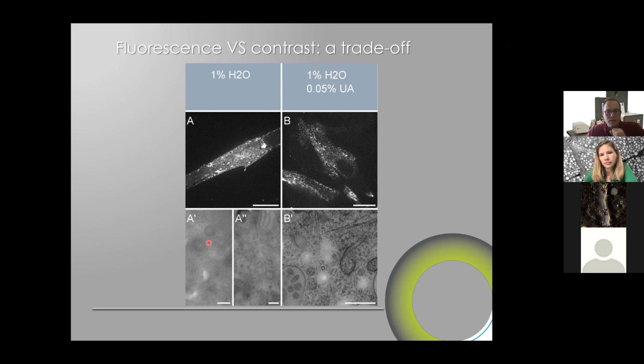We see barely anything. And then this is with post-staining. So the post-staining brings up a bit of contrast, but in no way it's comparable to what we got in the freeze sub cocktail having 0.05% of uranyl acetate. So I don't know how this works. I have no clue, but one thing is sure, having the UA directly into the cocktail during the freeze sub has a much better impact than the post-staining.